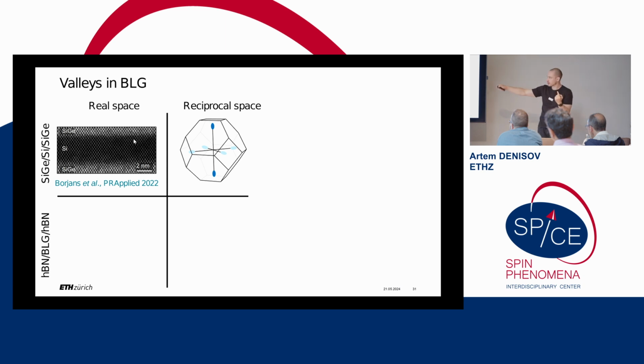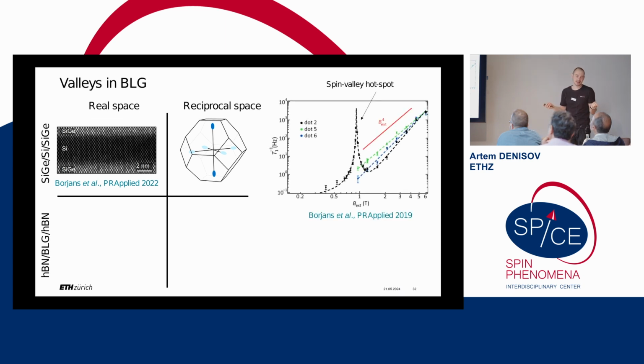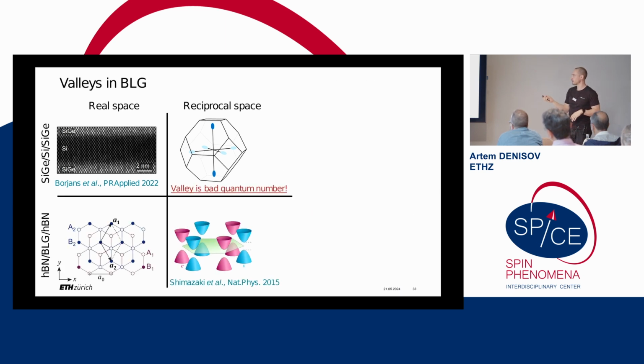And unfortunately, in the same direction, you have this atomic interface disorder between two materials. This disorder intrinsically couples your valley to your orbit, which is a super bad quantum number. As a result, valleys are one of the biggest enemies of the silicon community, because once, for example, your Zeeman energy is equal to the valley splitting, you immediately see that your relaxation time drops 4 orders of magnitude. So you really want to avoid the valley, and that's why people in the silicon community make quantum wells, for example, very thin to move the valley further in energy. So valley is a bad quantum number in silicon.